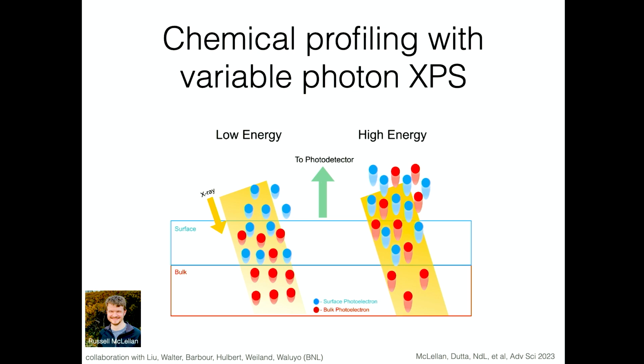So then we turned to much more detailed materials characterization of the surface oxide. This was all in collaboration with Brookhaven National Lab and led by Russell McClellan in my group. What we did was X-ray photoelectron spectroscopy. So you send in an X-ray, you kick out an electron, and then you use that to look at the chemical environment of the electron that came out. And because it's at a synchrotron at Brookhaven National Lab, we're also able to change the X-ray energy. That changes the sampling depth, because as you go to higher energies, you're more likely to see an electron from deeper away from the surface.